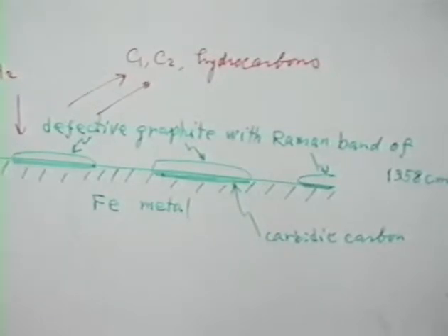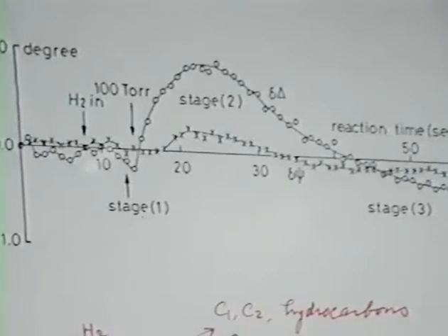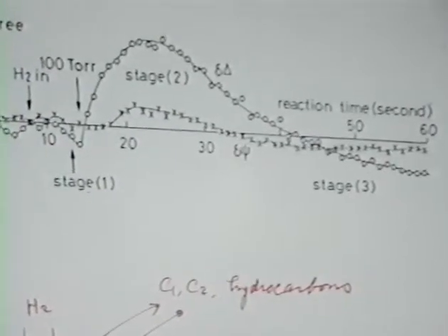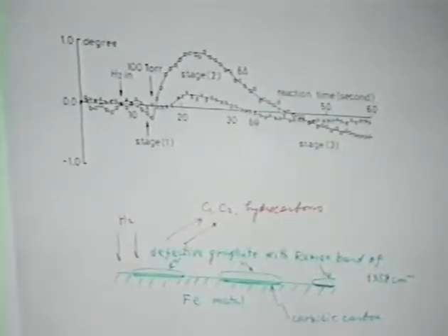With this sample, we introduce hydrogen at 400 degrees C. Here we observe again the drop in the delta and a small change in the delta psi. We believe at this stage there occurs some surface hydrogen, and at stage 2, perhaps the accumulation of a carbon complex takes place, and then production of the hydrocarbon follows, and we observe that decrease in the delta. So some of the complex curves can be well understood. Next slide, please.